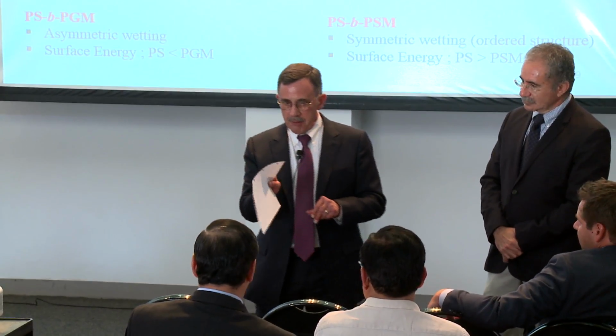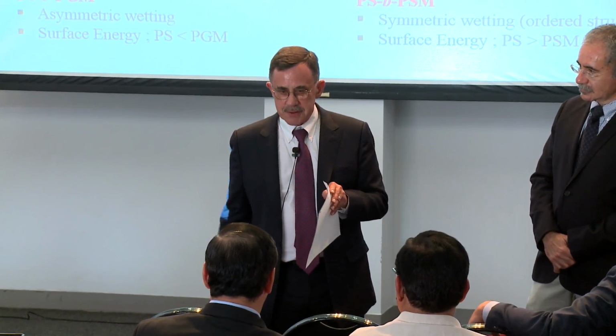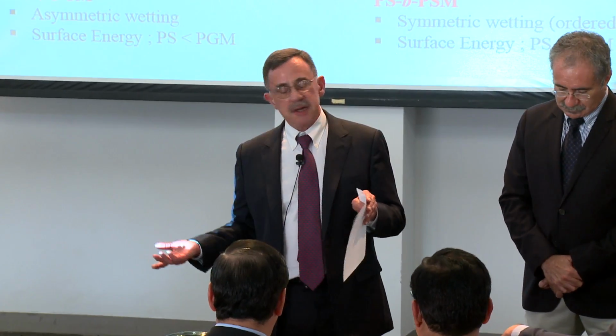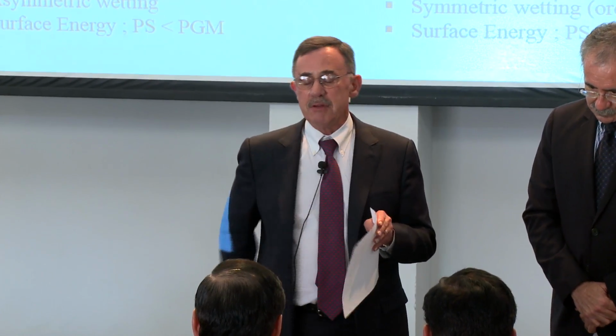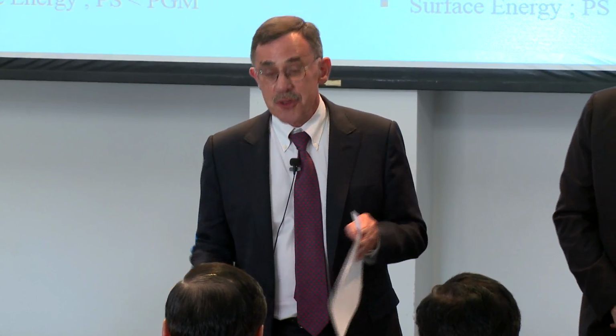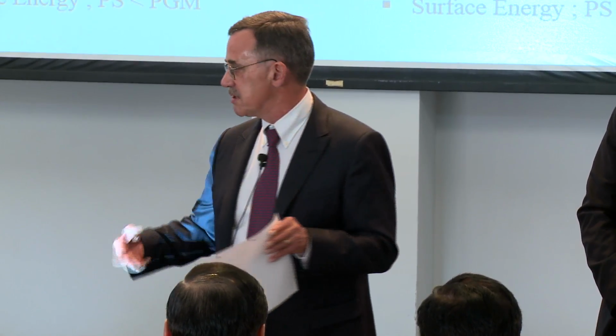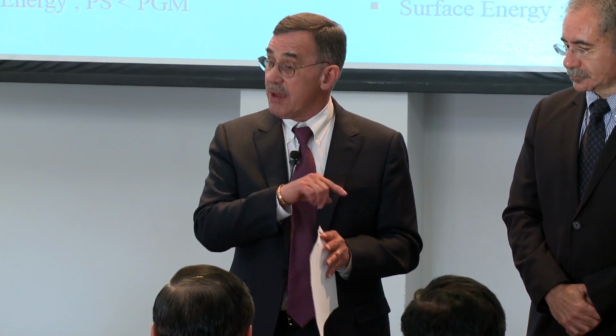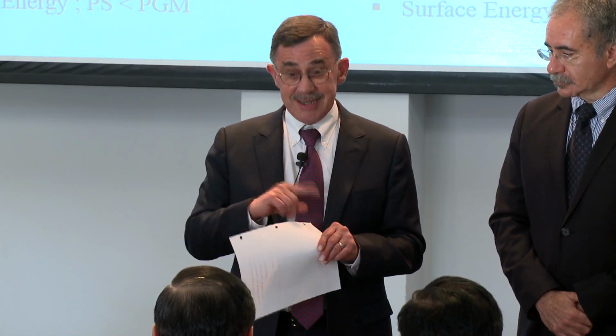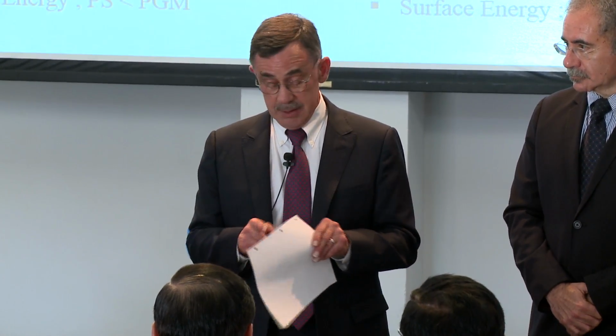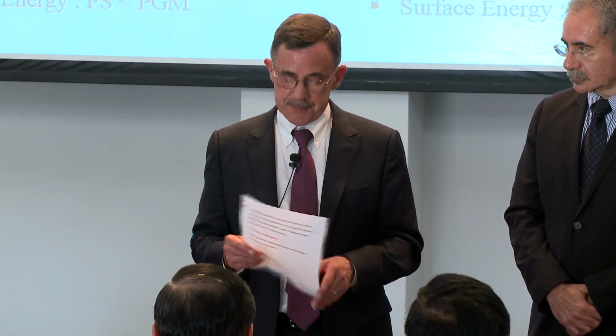I can give you these copolymer arrays, porous film normal to a surface. Right? And let me give you domains that are 10 nanometer in diameter, and I can backfill this now with a material that's a good thermoelectric. Some bismuth compound or other, whatever. And I can put electrodes on both surfaces, and now I have a thermoelectric device. Now, with a thermoelectric device, I apply a voltage across it, and the temperature on one side will be lower than the other. Just a simple device. Right? So I have a means by which I can use the copolymers to get heat out. All right? And the thickness of the film is about this.